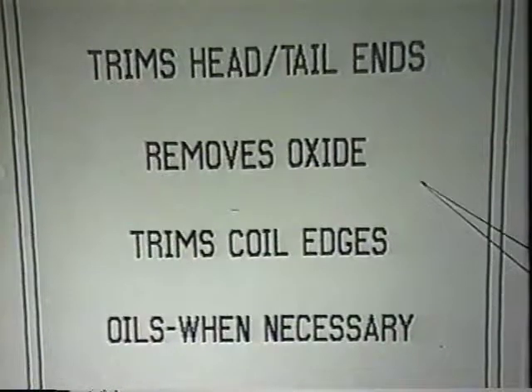The pickling operation is intended to remove that oxide, the oxide that occurs from the end of the finishing into the coil. If we don't remove that oxide, it's going to get pressed in later on in the cold reduction process. It's going to cause an imperfection, which is unacceptable for exposed application. So the pickling operation is there to remove the oxide.